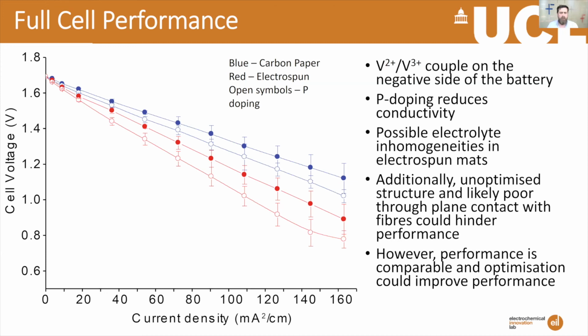And then to do that properly, depending on how long your measurements take and how big your tanks are, you might obviously deplete your electrolyte, which then changes the reversible potential of your system. So this is measuring the overpotential away from reversible potential. Obviously, if you change the reversible potential, you have to account for that as well. So that's one way of doing it, and that says, we've got fewer voltage losses at a higher current density, therefore the performance is better.